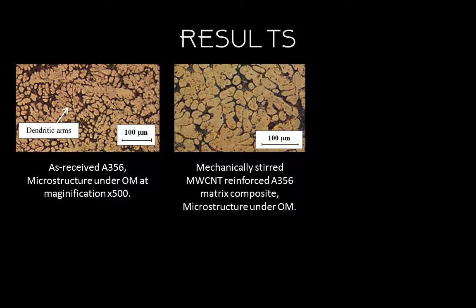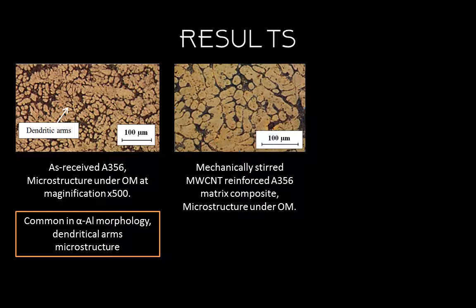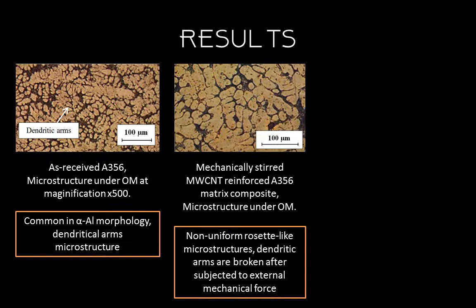Now let me show you the results. The first picture is the as-received A356 microstructure under OM at magnification of 500 times, while the second picture is the mechanically stirred MWCNT reinforced A356 matrix composite microstructure under OM. Did you see the difference? The first picture is the common alpha aluminium morphology with dendritic arms microstructure, while the second picture is the non-uniform rosette-like microstructure, proving that the dendritic arms are broken after being subjected to external mechanical force.